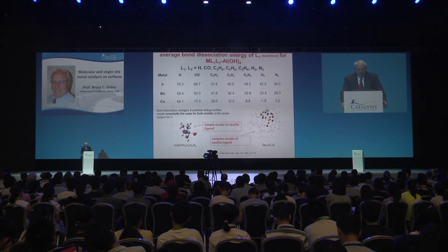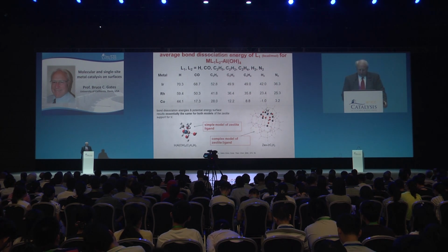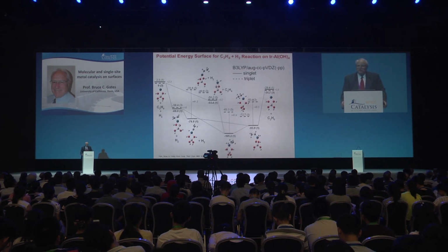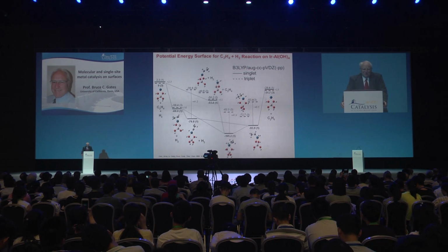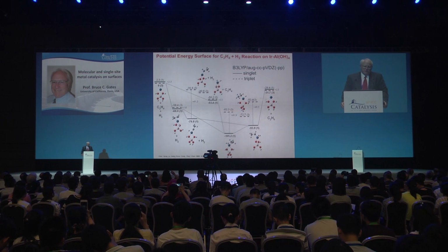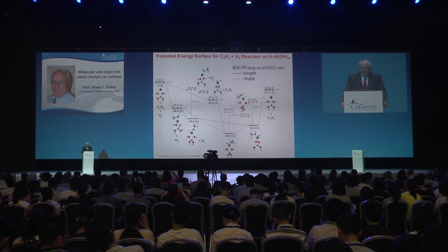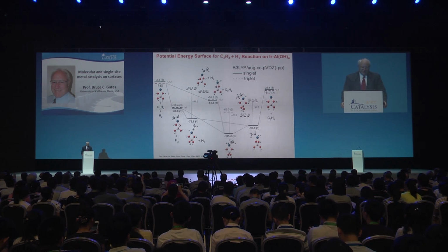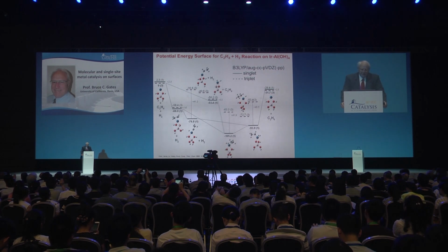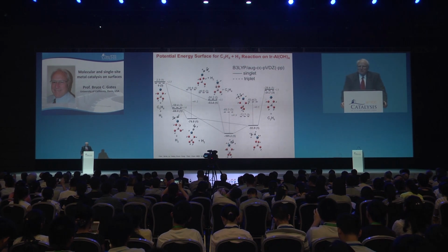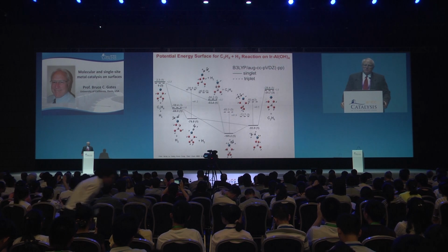So with such structures, one has the basis for making predictions about bond dissociation energies and steps in catalytic cycles. Here you see for ethylene hydrogenation, the calculations showing pi-bonded ethylene, hydride, ethyl, a catalytic cycle that one would expect. It looks like the Wilkinson hydrogenation.